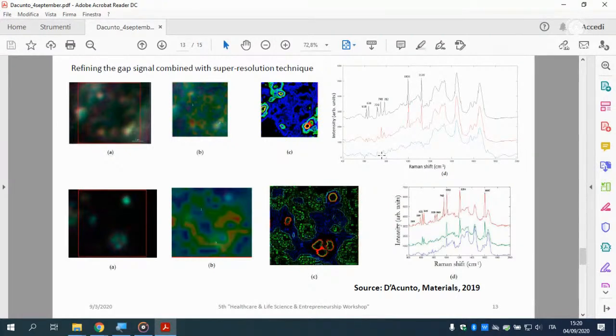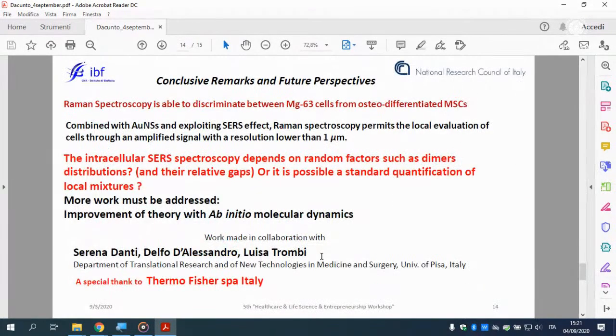This is non-SERS, this is SERS, this is theoretically a curve solving the spectral mixture of biomolecules inside this region. And so we have the appearance of a new mode that experimentally is observed only in part. This is another sample. We have this image of a trimer, but only 2 nanoparticles, the closest to each other, practically a dimer, increase the SERS signal. So we have a signal practically only from dimers.